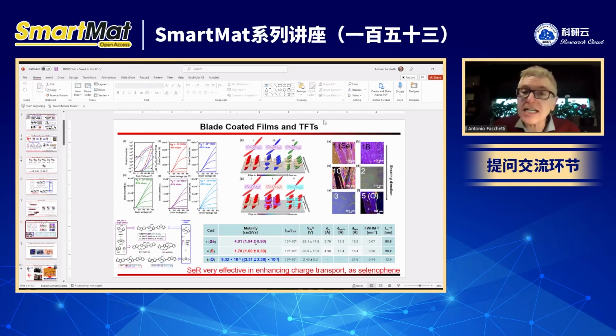You see here, this is an example of reproducibility. The reproducibility, the standard deviation is very, very large. You see from the maximum number to the average, you have a factor of 2. And this is because the way these devices were made is by blade coating, and so the quality of the film is not optimal. So in terms of stability, the devices are stable. In terms of uniformity, this is something we haven't studied, and it is shown here. The standard deviation is very, very large, right? It's 25%.